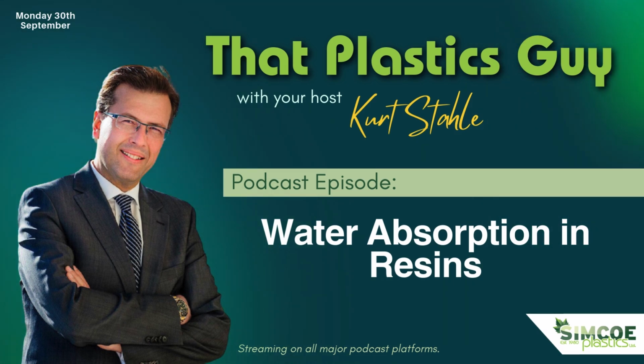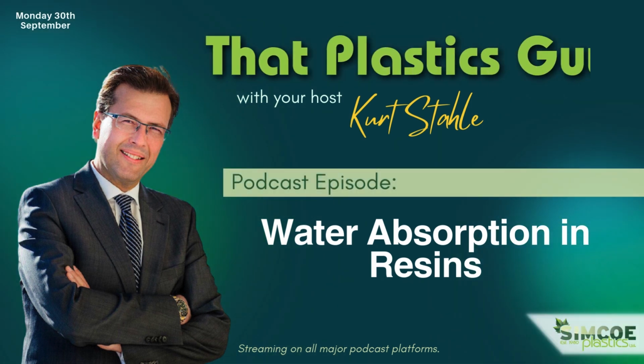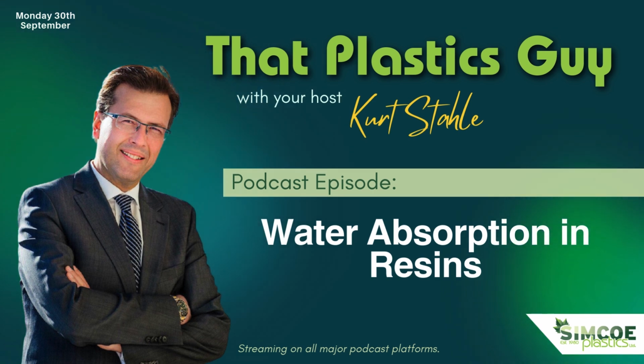Here we go. High density polyethylene. We talked about polyethylene and polypropylene not being too bothered by moisture at all. Its dry state 0.005, just like EVA. Its equilibrium 0.01. So it's very, very little moisture absorption. And again, run it through a hot air dryer on a particularly humid day, I'm thinking southern United States or Ontario on the worst days, knock that surface moisture off, and you're just guaranteeing that you will be able to process a great part.